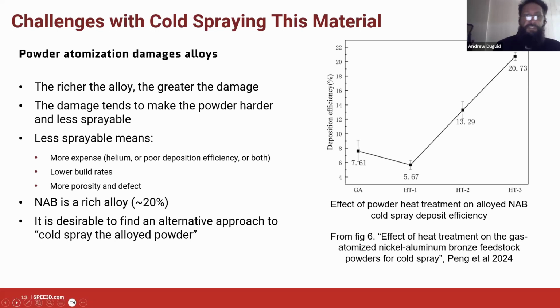So what that means is that you're bucking all of those other things: higher expense in terms of getting greater nozzle energies, or living with poorer deposition efficiencies and lower build rates. And a critical one for us is what you're left with in terms of porosity and residual defects. Obviously NAB is quite a rich alloy, its alloy content is about 20% and it's quite hardenable.